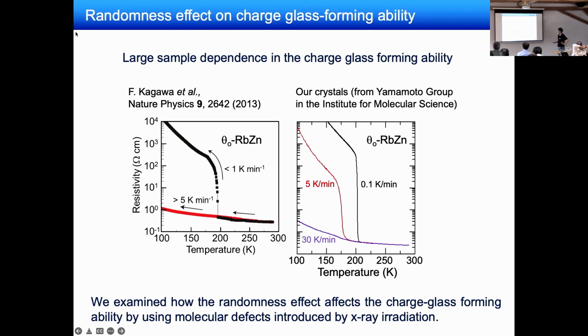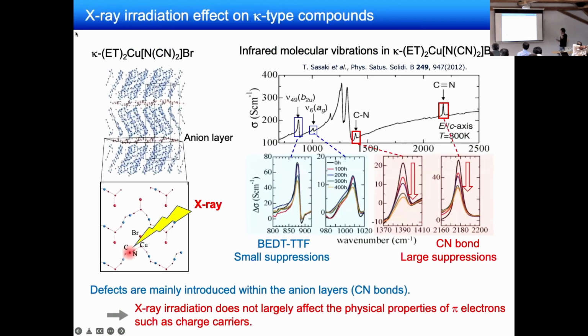Then we decided to investigate how the randomness affects the charge glass forming ability by using molecular defects introduced by X-ray radiation. It is well known that X-ray radiation is a powerful probe to introduce molecular defects in organic materials. This figure shows the X-ray radiation effect on the molecular vibration in a kappa type BEDT-TTF compound. Large suppression has been observed in the CN bond in the anion layers compared to that of the BEDT-TTF molecule. These results indicate that molecular defects are mainly introduced within the anion layers. Therefore, X-ray radiation does not largely affect the physical properties of pi electrons, such as charge carriers.